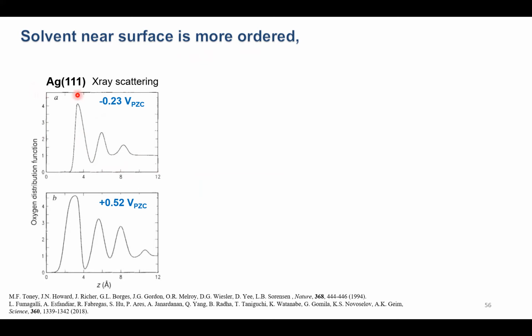Here we're showing experimentally measured X-ray scattering measurements of the oxygen distribution function for water near a silver electrode surface. And we see these very sharp peaks within a few angstroms of the electrode surface, showing that water is more ordered, right? It has higher peaks in density than bulk water.